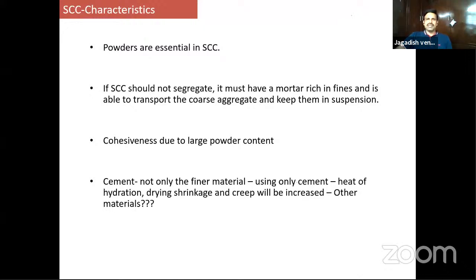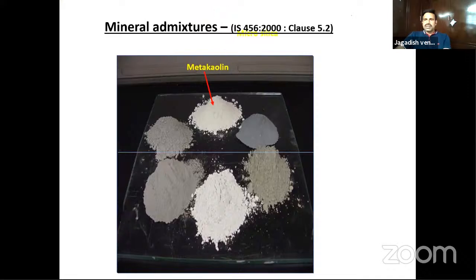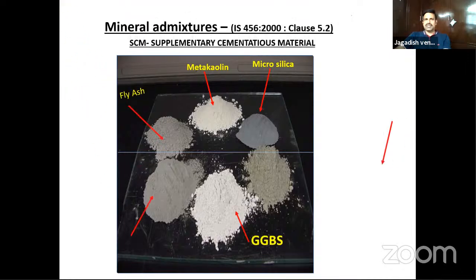And this powder content will keep the coarse aggregates in suspension during the flow. And also it will give a lot of cohesiveness to the concrete. So beyond 450 kg, you have to use powder content in SCC. So you have to look for other powders. As IS 456 clause 5.2 allows you to use a number of mineral admixtures, as I mentioned, starting from fly ash, GGBS, ultrafines, microsilica, metakaolin, rice husk ash, and so on.